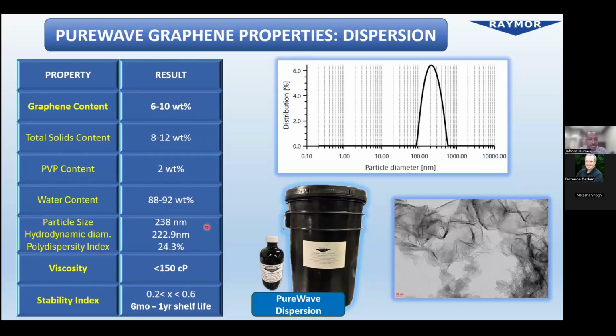With very good particle sizes, 238 nanometers, and do so with very reasonable viscosities, less than 150 centipoise. And you would think that maybe with the thickness of such a solution, it would lead to great instability, but we've found that the stability indexes are very good and that the shelf life can be anywhere from 6 months to 1 year or even more with our testing and those done with partners as well.